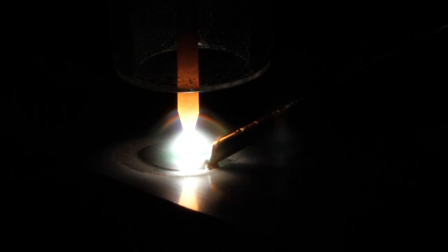When initiating the arc, we need to spend a moment getting heat into the part. The thicker it is, the longer we have until the weld pool forms. This weld pool is recognized as a wetting of the material and should have a bright luster as it becomes fluid. Once the weld pool has formed, we can begin adding the filler rod and moving the torch along the weld.